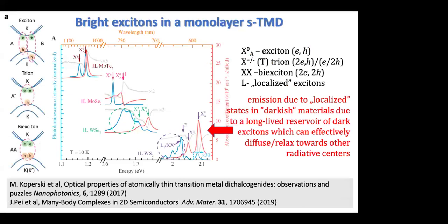And this is the comparison of the spectra for several semiconductor materials. We can see the results are from low temperature, but still you can appreciate several facts. First is, of course, we already told that going from telluride, molybdenum ditelluride, up to the tungsten disulfide, you can cover quite a broad energy range. But there is also another feature, very important. If you look at the spectrum from molybdenum diselenide and tungsten diselenide, you will see that the first one is composed of very well distinguished two peaks. One is due to trion and the other is due to neutral exciton.